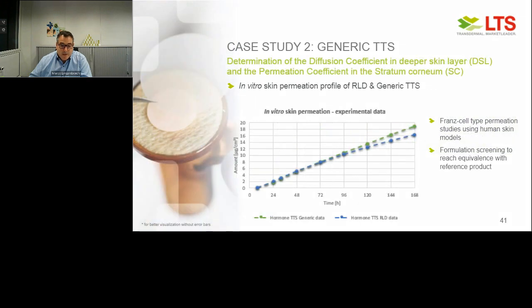In the next step, we again run permeation studies using Franz cell type skin permeation, but using a human skin model here as a barrier function. We are running the study over 7 days, and again in blue we see the reference listed drug and the pretty constant generic formulation. You see here it's a bit more constant over the last 4 days compared to the RLD. So slight differences in the formulation can be identified here. Usually formulation screening is done with this concept until we have a pretty equivalent product. In this case, it's not 100%, but pretty close.